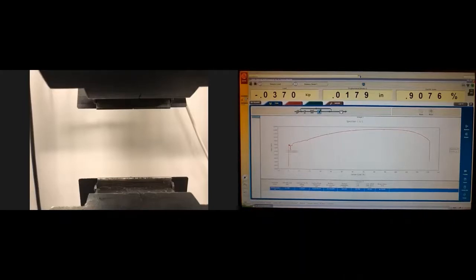plateau. So you see some lower boundary and upper boundary. So it is where atomic planes start to move and slip occurs. So dislocations are generated, and they're moving across the grains and throughout the volume of material more and more, starting right over here. And at some point, dislocations will be activated in probably most of the slip systems available in the material, and they will start propagating across the grains and volume, and then they are still generated, and then they move and allow the deformation of the material.